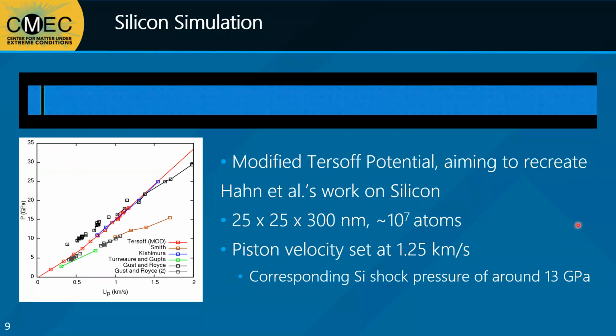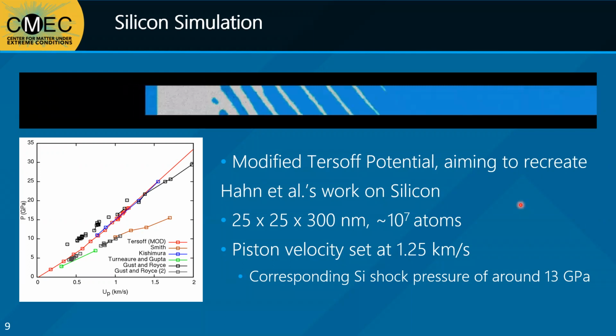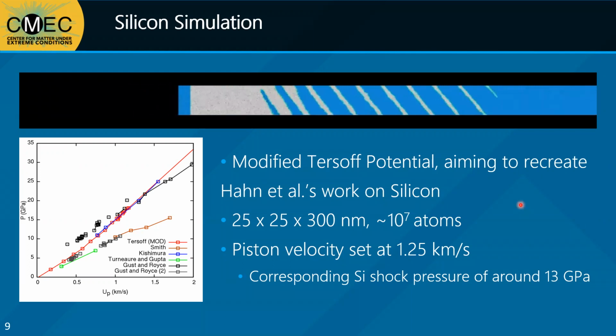This simulation was 25 nanometers by 25 nanometers by 300 nanometers, containing around 10 million atoms. The initial temperature for the silicon bulk was set to 300 Kelvin. We varied our piston velocity for these simulations between 0.9 and 1.5 kilometers per second, and the video seen here is going at 1.25 kilometers per second. At this piston velocity, the corresponding shock pressure should reach around 13 gigapascals, which is above the threshold expected for